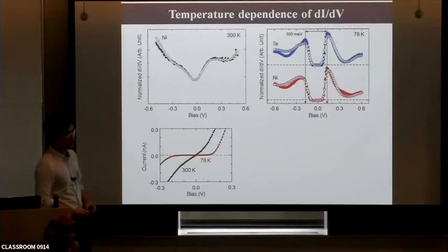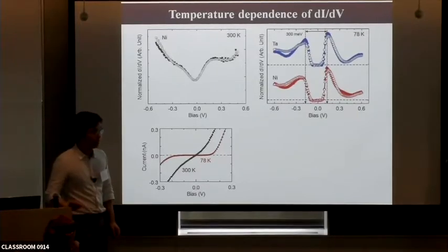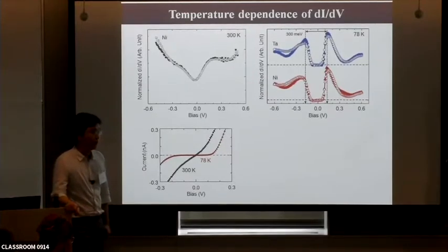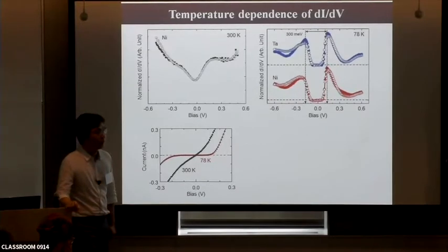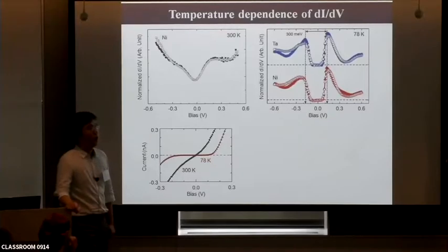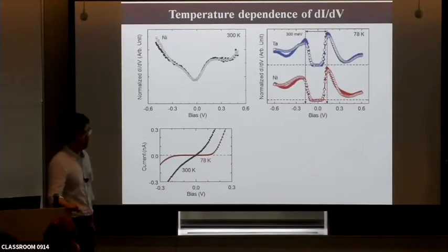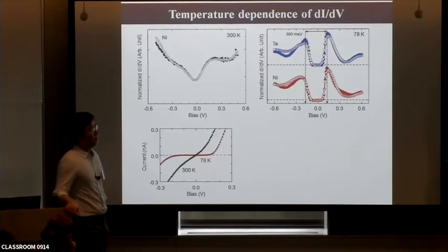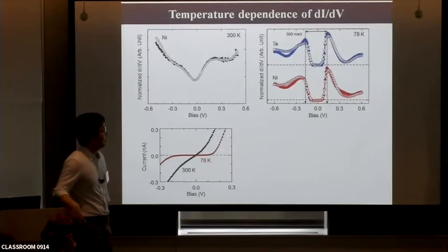Yeah. Okay. Now, the other thing, which is just wild speculation: we heard from Malta's beautiful talk and others that in the excitonic insulator phase there is a symmetry breaking, inversion symmetry breaking, which leads to a little bit of structure in the density of states. The point of minimum band gap is not exactly at the gamma point. There's a little bit of asymmetry. So my question, would that show up in a QPI measurement, which sort of shows the Fermi surface? Is there a way to see that in your experiments? I mean, it's a delicate effect, it's long wavelength, but could you see that off-centering somehow, for example, by QPI?